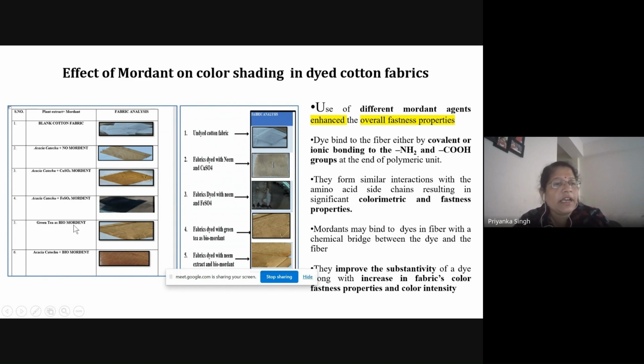Similarly, for the green tea, first we treated the fabrics with the green tea only, without adding any acacia or anything else. With the green tea, we observed a very light brown color. But when we used the extract containing the babool (acacia catechu) with this green tea, we got a very good dark brown color. We saw a similar finding for the neem extract also. After treating the cotton fabrics with neem and copper sulfate, we obtained a gray color. So similarly, the color variation is mainly due to the use of the specific mordant, which improves the association of this dye with the cotton fabrics across the amine or carboxyl groups present in the polymeric unit.